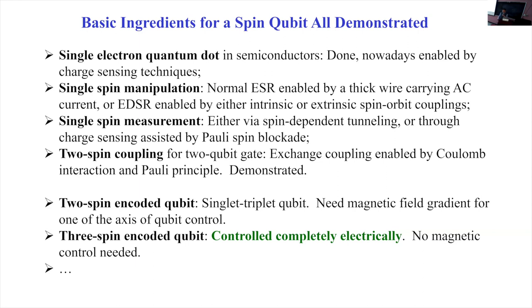For single spin manipulation, people already demonstrated both regular ESR and EDSR, the electrically driven or electric dipole spin resonance. So either way, using intrinsic or extrinsic spin orbit coupling, you can rotate spins and put them into nice coherent superpositions. Single spin measurement has been done either with spin-dependent tunneling. It turns out you can apply a big magnetic field, split the spin up and down states, and stick a reservoir with Fermi level in between those. And then you can do spin-dependent tunneling. So that allows you to do single spin measurement as well, together with a charge sensor, or using the Pauli spin blockade to measure spins.